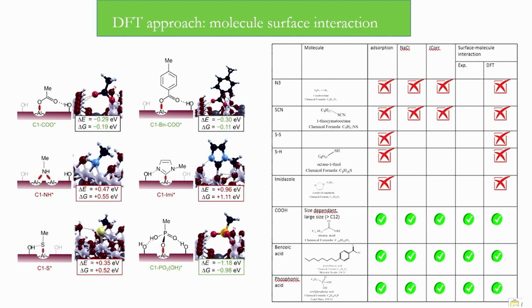Using this model, we studied all the molecules. Fortunately, we found that molecules which are not active as inhibitors are also those for which the adsorption on aluminium is endothermic, whereas for inhibitor molecules the adsorption is exothermic. There was good agreement between calculations and experiments.